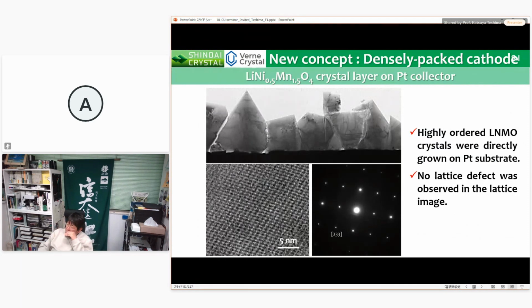These are TEM images of LNMO crystal layers on the platinum substrate. As you can see, highly ordered LNMO crystals were directly grown on the substrate. No lattice defect was observed in the lattice image.